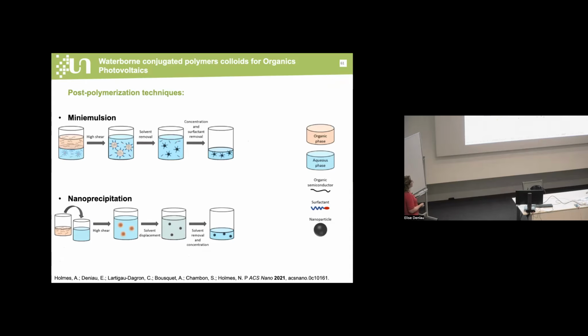In order to form nanoparticles of semiconducting material, we use post-polymerization techniques that are well used: the mini-emulsion technique and the nanoprecipitation technique. By mini-emulsion, the nanoparticles are formed from an emulsified droplet in water, whereas by nanoprecipitation, the polymer precipitates in the solution. In both cases, the solvent is removed by evaporation under high temperature. What is very different is that by mini-emulsion, we use two solvents that are immiscible, water and solvent, and so we have to use surfactant, whereas by nanoprecipitation, we don't use surfactant and both solvents are miscible.